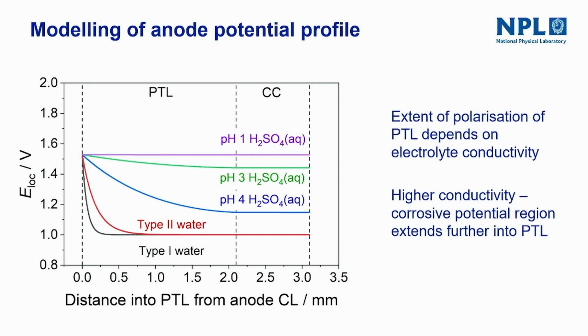So you have deionized water, type 1 water and type 2 water in red, and you can see that there is a sharp potential drop over the length scale of a couple of hundred microns. So actually most of the porous transport layer and all of the bipolar plate is sitting at its open circuit potential, rather than at the high potential of the electrode that you would predict if you read any other papers or talked to anyone who worked for an electrolyzer manufacturer.